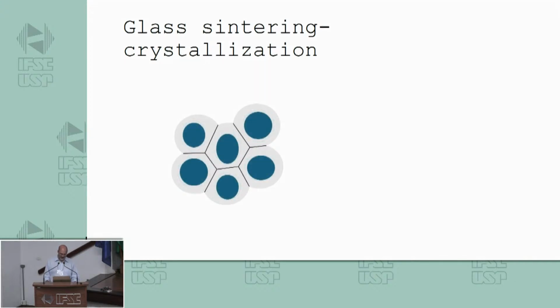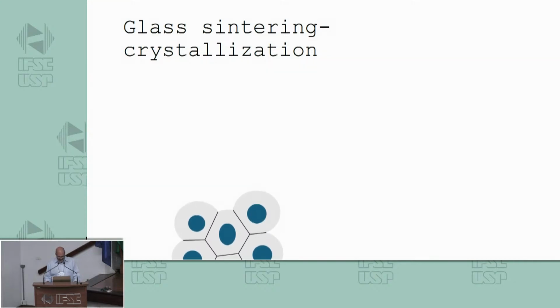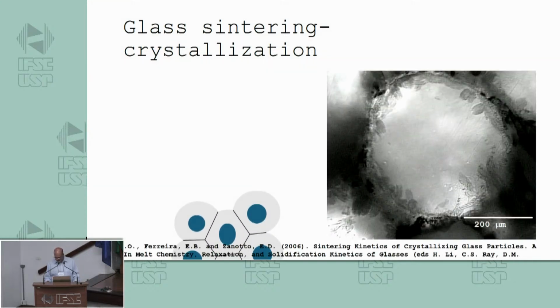That's a way to get volume crystallized glass ceramic from glass particles. Here you see spherical glass particles with some crystals growing from the surface after they got sintered.